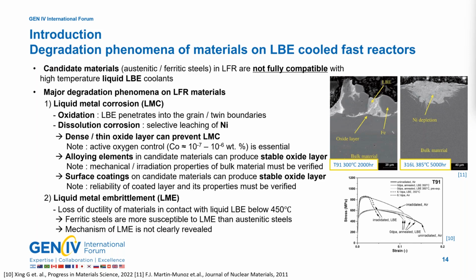The previously introduced candidate materials in LFR are not fully compatible with high-temperature liquid LBE coolants. Major degradation phenomena in LFR materials can be broadly divided into two categories. The first is liquid metal corrosion, represented by the selective leaching of nickel. In a liquid LBE environment, forming a stable oxide layer that provides corrosion resistance can be achieved through alloying elements in candidate materials or surface coating on structural materials. For this, active oxygen control is essential.